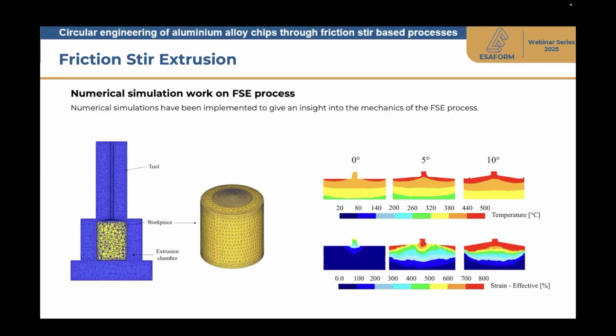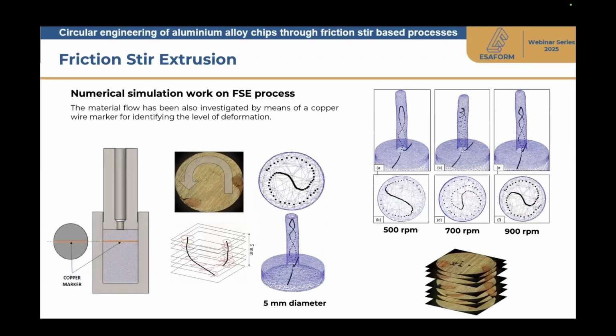And again, a numerical model was proposed and introduced for this operation, in order to understand the temperature distribution during the process all along the section of the billet and the extruded wire, but also to properly investigate the material flow actually occurring in the extrusion mechanics during the process itself. In this way, it was possible to highlight that a sort of spiral movement is observed. Here it is shown both with a node tracking approach in the software used, but also with some markers in the experiments.